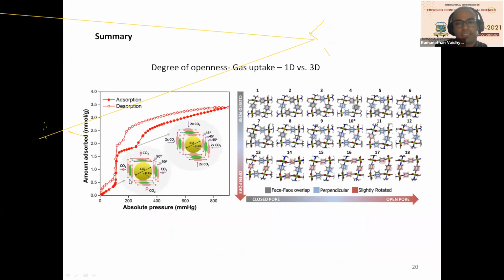Now, in summary, what we have seen is that initially we are able to let in only one CO2 per unit cell. That is the 1D form, because only one direction is available for the CO2. But when you rotate it using this whole range of configurations, which we have mapped, and rotate it to a specific angle, which is 45 degrees in this case, we are able to get the maximum openness. At that point, the MOF becomes a 3D open MOF. That explains how this happens. Also, here you can see the open pore is represented by a dark red color and the completely closed form by a dark gray. As you rotate the pyridyl groups, you are moving from one configuration to the other, and the configurations which have the maximum number of pyridyl groups at this 45 degree angle have the maximum